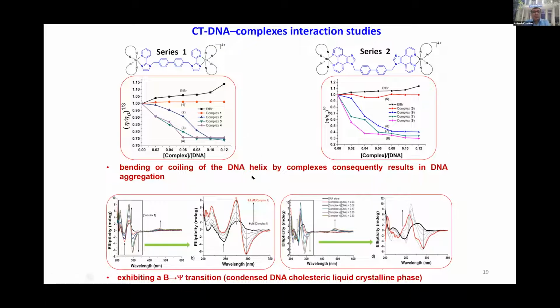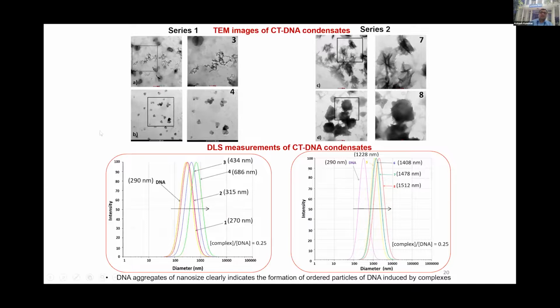We have also seen the bending or coiling of the DNA helix by complexes by using circular dichroism spectroscopy, which shows the B to Psi transition of this condensed liquid crystalline phase, indicating the condensation. Several other techniques such as imaging techniques, such as TEM, evidence that these structures are really condensing into nano condensates, and dynamic light scattering measurement also indicates the condensation of the DNA by increase in the size of these nano aggregates that are formed because of the interaction of these complexes with nucleic acids.